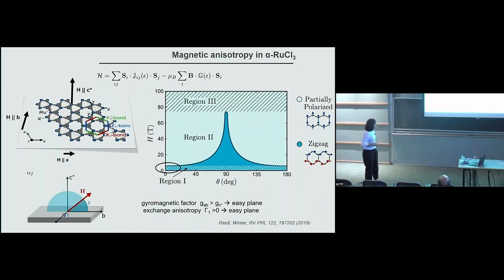So what I'm trying to show here is this magnetic anisotropy. For instance, if you put here would be to put the magnetic field parallel to the plane, and here would be to put the magnetic field perpendicular to the plane. So the fact that the gyromagnetic factor is anisotropic and the exchange anisotropy is positive, this system has a very strong easy plane anisotropy.